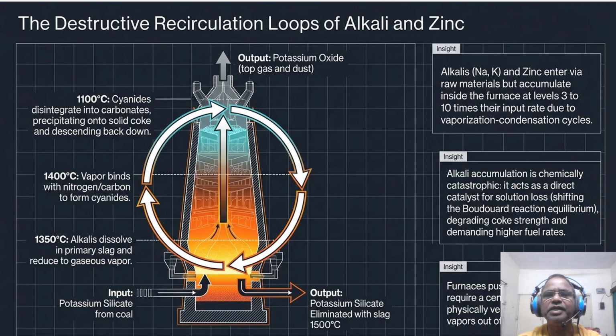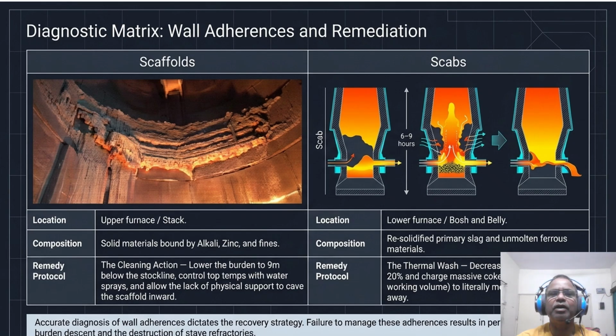So high PCI furnaces require a strong central gas flow specifically to vent these volatile vapors out of the loop before they can recondense, and this is one of the most fundamental rules for all operators to follow religiously. When these recirculating chemicals finally stick to the wall, they form a permanent obstruction, as we know. Coming to the diagnostic matrix, wall adherence and remediation. So we must differentiate between the scaffold and the scab. This is a very important fundamental that is to be differentiated.